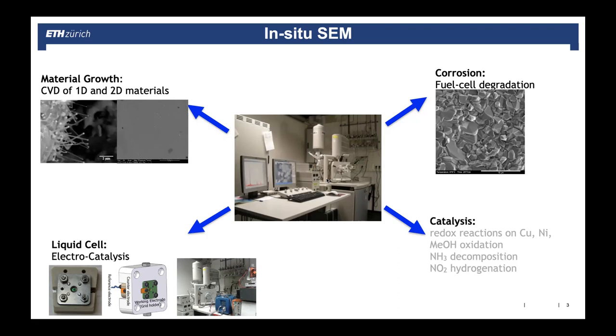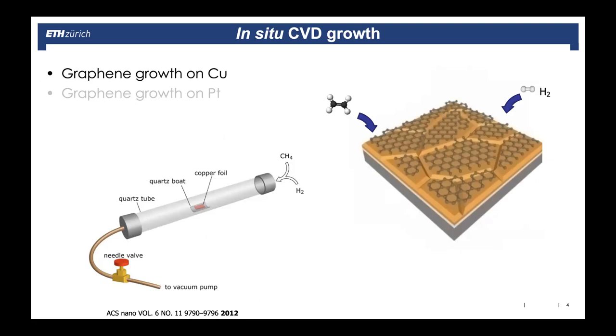So, yes, today's talk on this 2D workshop is the growth of graphene. There was this huge hype after the Nobel Prize was awarded for graphene, and people tried to grow graphene. The peeling with a gluing tape is a bit tedious. So one way to get graphene is to grow it by chemical vapor deposition, so CVD growth. And what you do there is you have a metal substrate, most often copper, but you can try nickel, iridium, rhodium, ruthenium, different metals work. And you heat up that metal substrate to quite high temperatures, like 900 degrees.